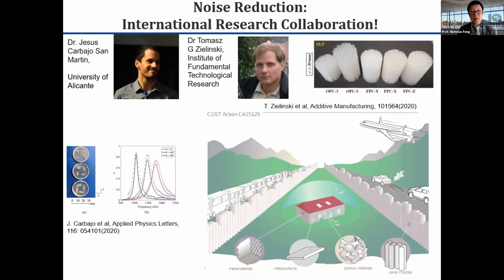Professor Jesus Carbajo San Martin, actually from University of Alicante, came and collaborated with us on the now, again, thin and air permeable microperforated acoustic absorbers, and we see that it is indeed possible to reduce the overall thickness by leveraging some unique channel designs, as well as increasing the acoustic boundary layer thickness in those fine features.